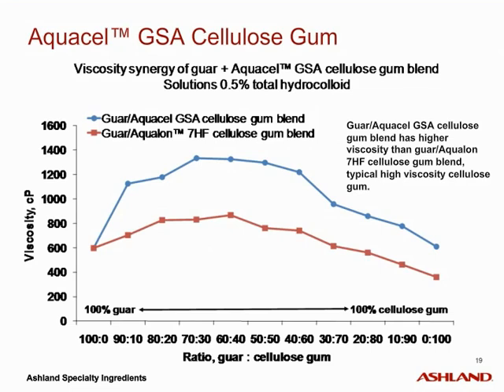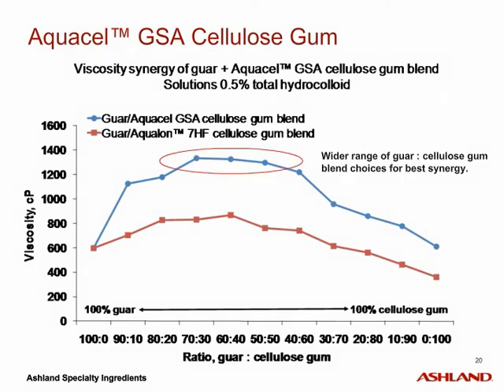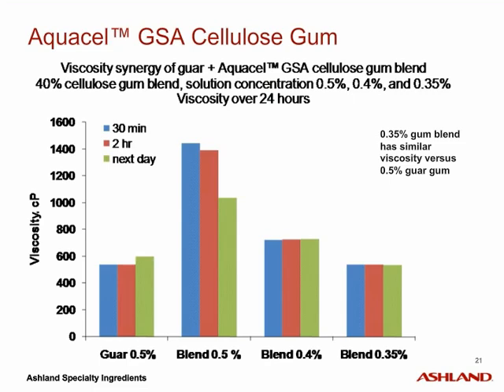We are also introducing Aquacel GSA for customers with stringent GMO requirements. Blends of guar gum and Aquacel GSA cellulose gum also show excellent viscosity synergy, much greater than standard high viscosity cellulose gum. It was also observed that the synergies could be realized over a wide range of ratios of guar gum and Aquacel GSA. Dosage analysis of 60-40 blends of guar and Aquacel GSA cellulose gum revealed that use levels of 0.35% gave viscosities over time similar to guar gum alone at 0.5% by weight. Again, less dose means less overall guar is needed.